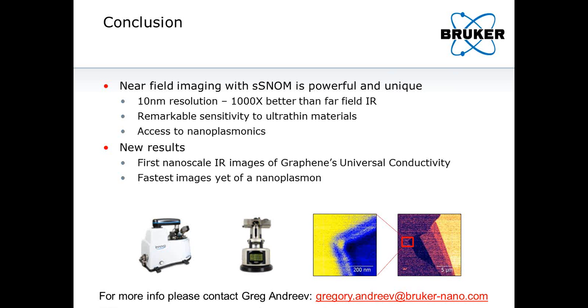Yes, that is true. The sample also scatters some background light, which you do not want to measure. You isolate the near-field light from this background light by looking at the parts of your detector voltage which are modulating at higher harmonics of the tip frequency. That is one way to isolate the near field from the background. The background will not modulate at higher harmonics, and it's not really affected by the tip-sample separation at the nanoscale, whereas the evanescent waves are. So that's one way you can distinguish the two.